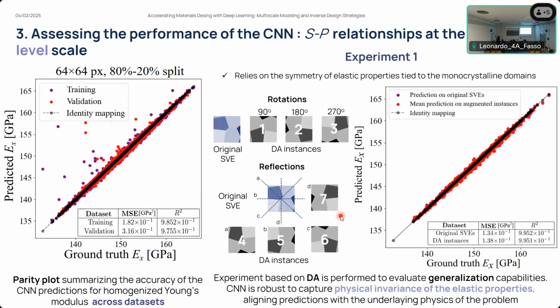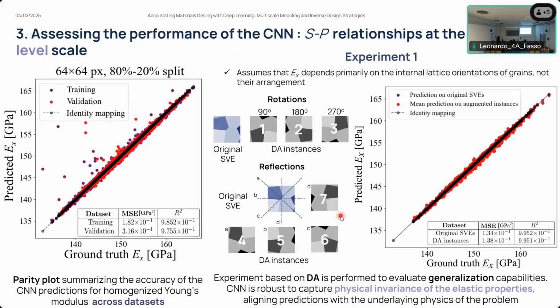In this case, this procedure relies on the symmetry of the elastic properties that is tied to the monocrystalline silicon domain in such a way that the transformations that we are applying to the original image maintain each grain lattice orientation unchanged, and we allow the position inside the stochastic volume element to vary. And the underlying assumption of this experiment is that the effective elastic property of the stochastic volume element depends primarily on the internal lattice orientations rather than on their individual arrangement within the stochastic volume element. We observe a very good agreement between the predictions of the CNN versus the ground truth data.